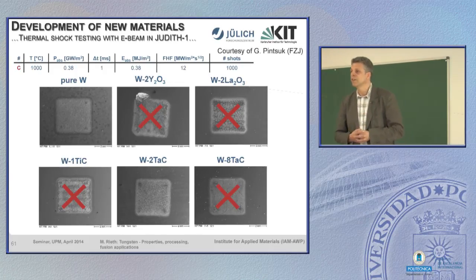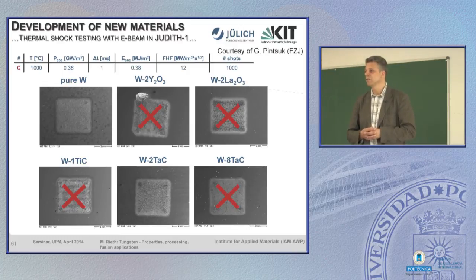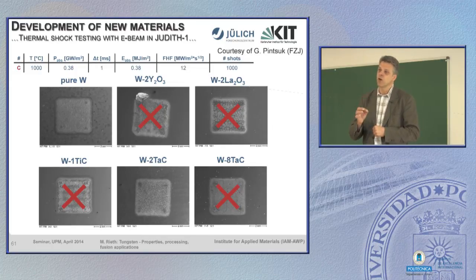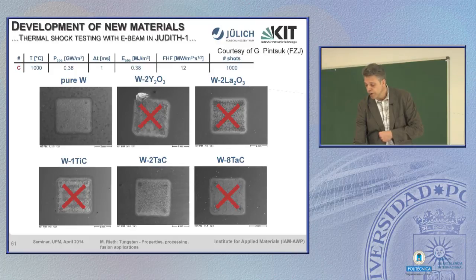This means we have to load them with high heat load, and the worst case scenario is not only high heat load, but shock loading. That's short pulses by electron beam with a very high heat load. And after 1000 shots, materials look like that. The pure tungsten shows almost no change. But for example, here you see a crack network, and also the other one shows a crack network, and this is what you don't want to have.